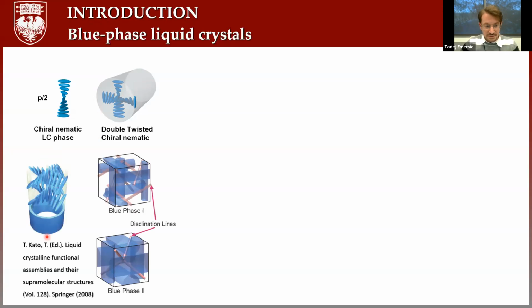These double twisted cylinders spontaneously organize into crystalline structures, as we can see here, and this is known as a blue phase. These double twisted cylinders can organize either in a simple cubic crystalline structure known as blue phase 2, or in a body-centered cubic crystalline structure known as blue phase 1. Because these double twisted cylinders cannot tile the space, disclination lines appear, or defect lines that stabilize the structure itself.